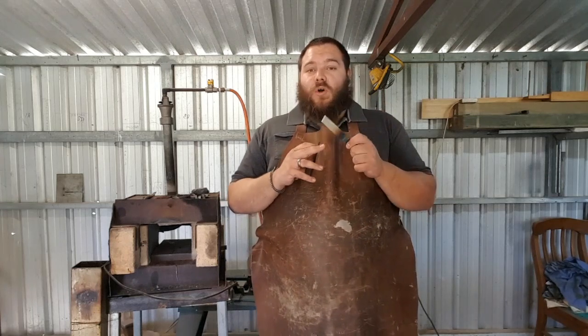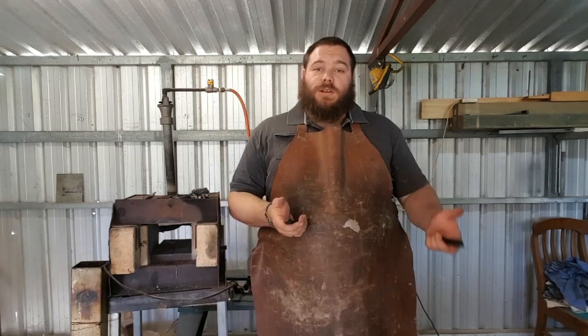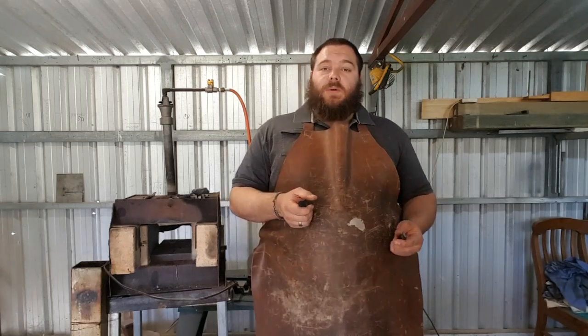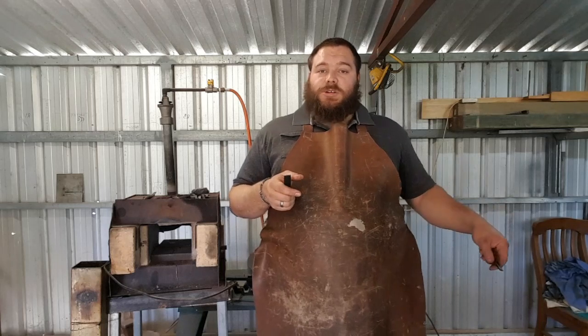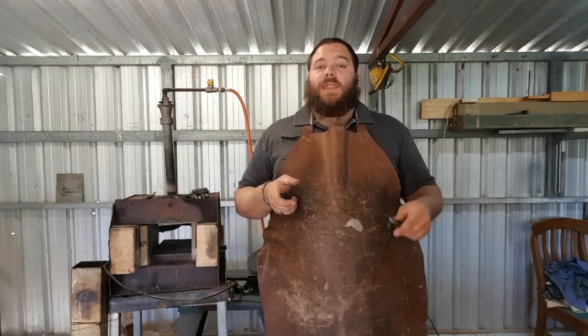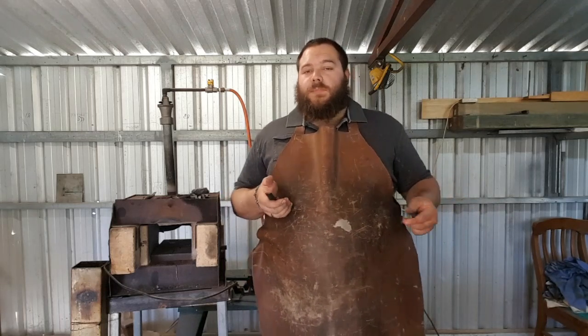Torch tempers tend to only do the surface if you do it once. Most old blacksmith books tended to tell you to temper 3 times. If you quenched a chisel, for instance, you would quench the chisel, scrape the scale off really quickly, quench just the tip, and then scrape the scale off really quickly, watch the colors run, quench the tip, scrape the scale off, watch it run again, and do that as many times as you could before the heat ran out of the body of the piece.